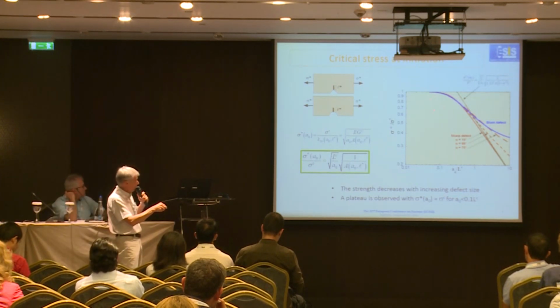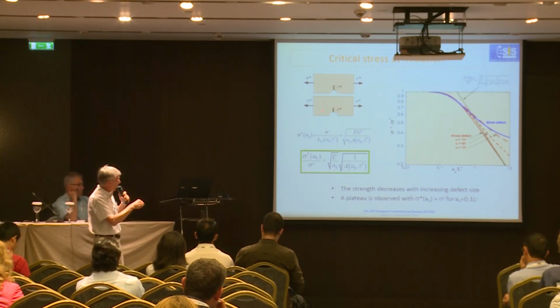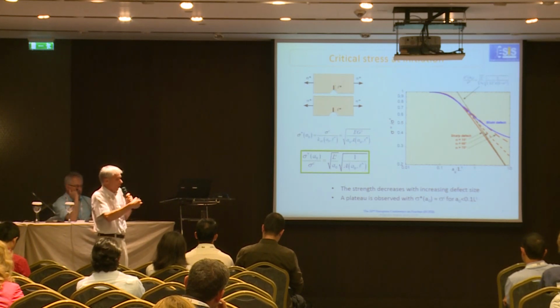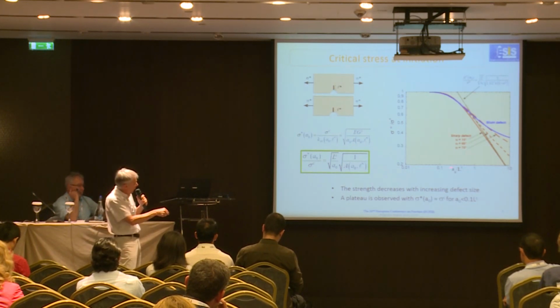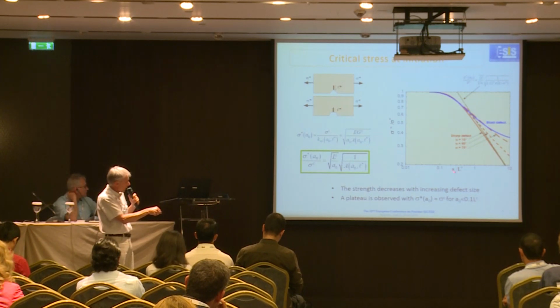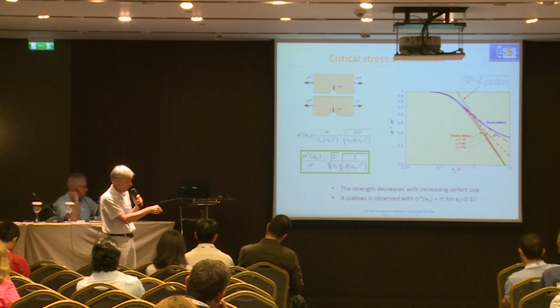And what is interesting here is that you have a plateau. That means that the strength of the ceramic with the flaw reaches the intrinsic tensile strength, that is to say the strength without any defect, if the size of the defect is small enough as compared to the characteristic length.